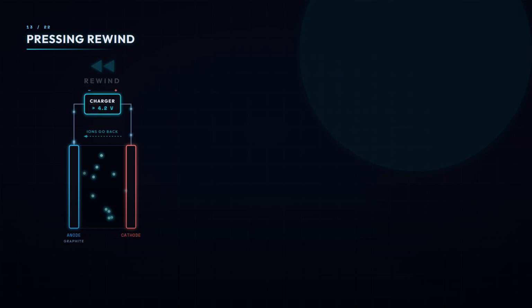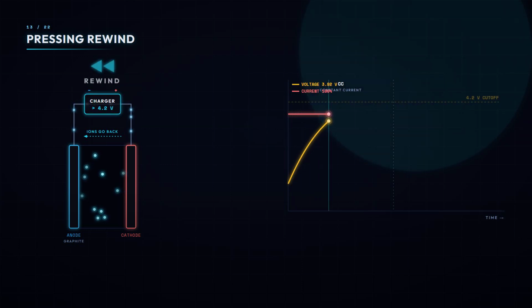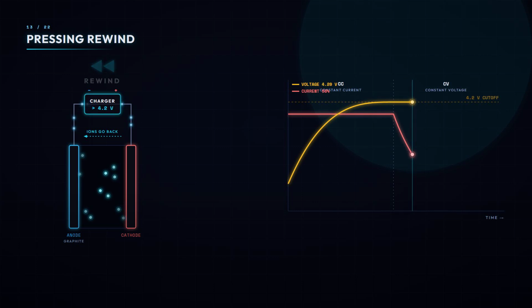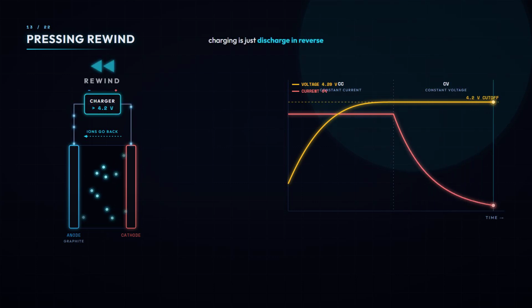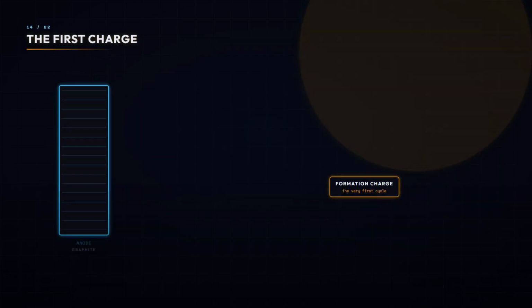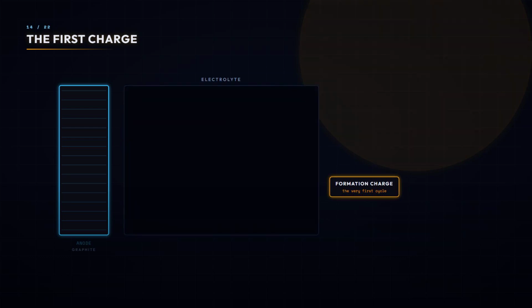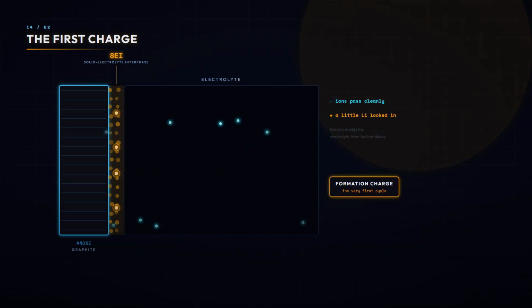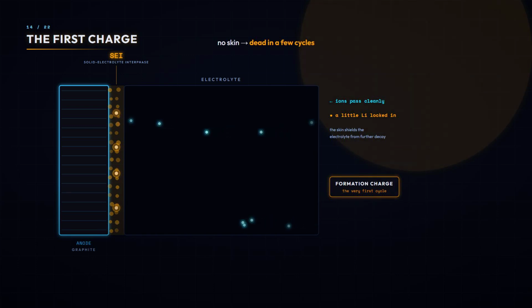Charging is just pressing rewind. A charger applies a higher voltage to force everything backward. First constant current until the cell reaches about 4.2 volts, then a held voltage while the current quietly tapers to full. But the very first charge does something hidden. The electrolyte breaks down on the graphite and builds a microscopic skin, the SEI. It permanently traps a little lithium, yet shields the electrolyte from further decay. Without that skin, the cell would die in a few cycles.